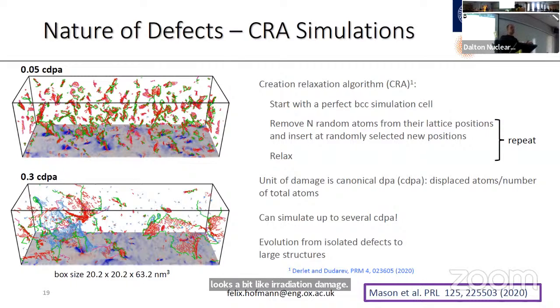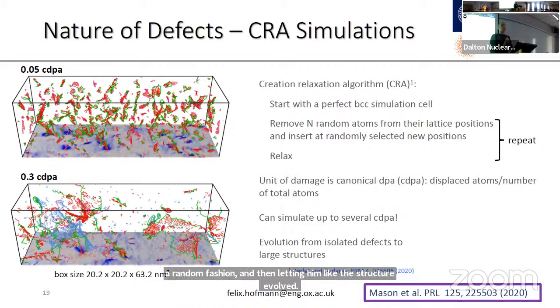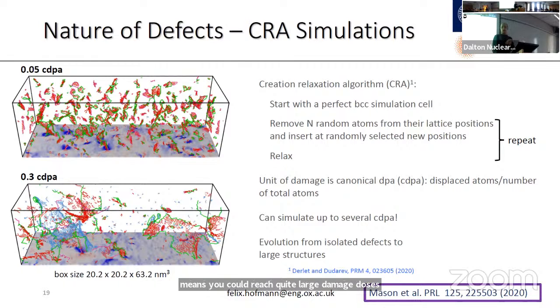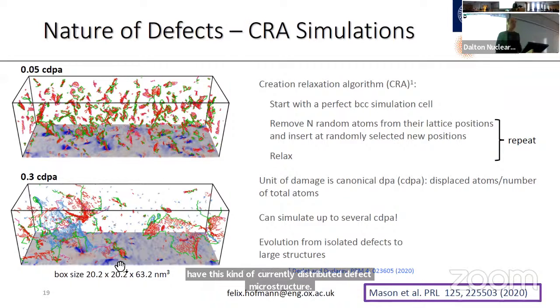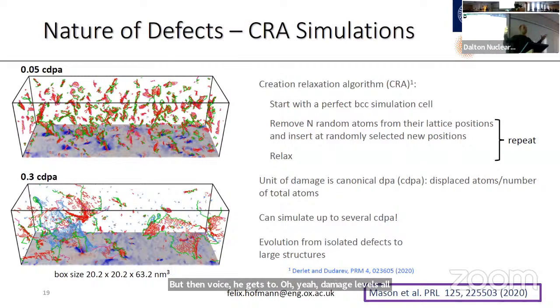So you're no longer doing full cascade simulations; you're just generating Frenkel pairs in a random fashion and then letting your microstructure evolve. The reason this is attractive is that it means you can reach quite large damage doses, several dpa, in reasonable times, and for reasonably large boxes, which is important for clustering. What you see at 0.05 dpa is a randomly distributed defect microstructure, but once you get to higher damage levels, your defects actually start to link up and form extended defect networks.